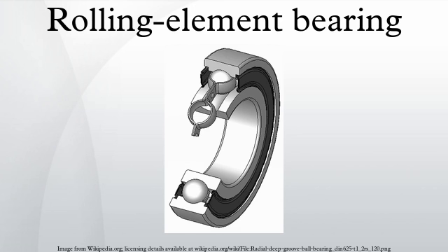Bearing failure. Rolling element bearings often work well in non-ideal conditions, but sometimes minor problems cause bearings to fail quickly and mysteriously. For example, with a stationary load, small vibrations can gradually press out the lubricant between the races and rollers or balls. Without lubricant the bearing fails, even though it is not rotating and thus is apparently not being used. For these sorts of reasons, much of bearing design is about failure analysis. Vibration-based analysis can be used for fault identification of bearings.